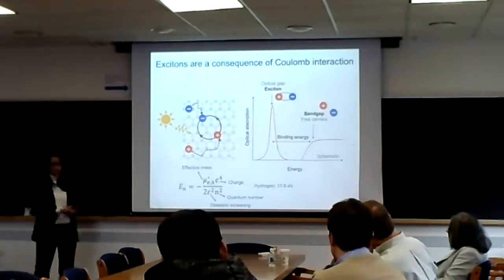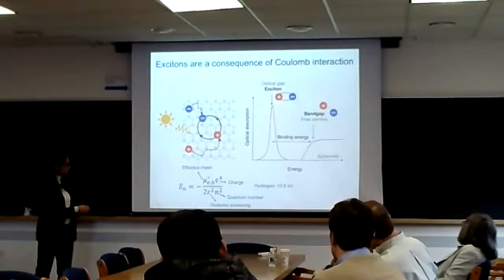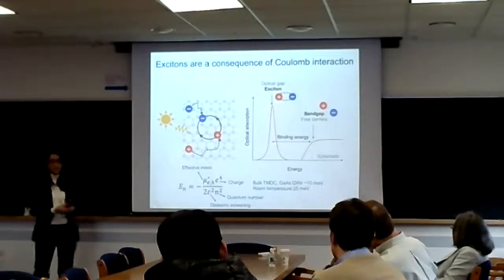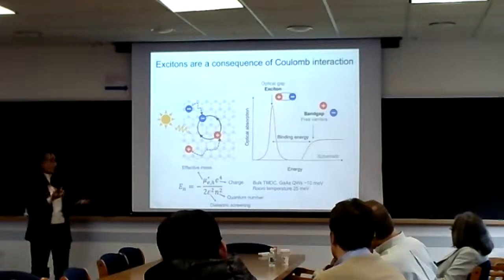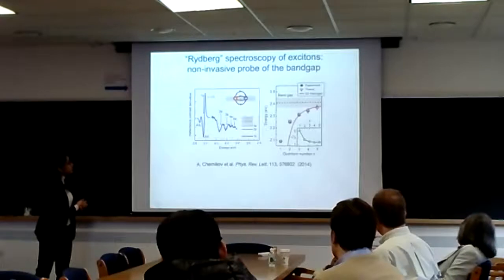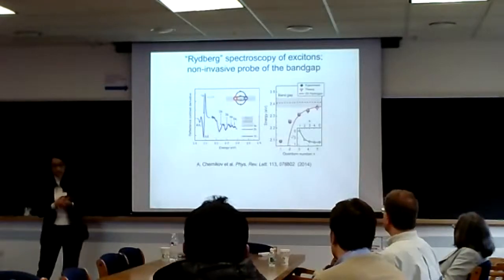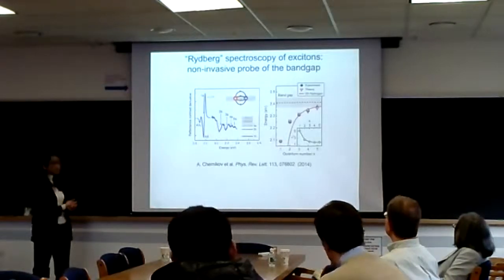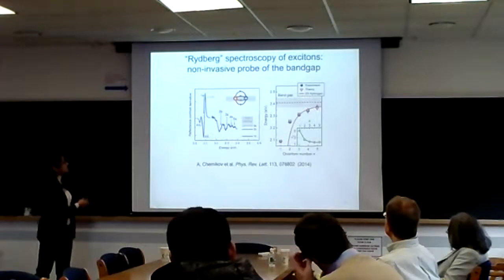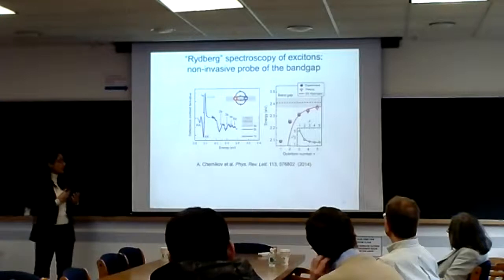Now let's work our way down to real systems of semiconductors. The effective mass goes down by an order of magnitude, and your screening goes up by an order of magnitude, and so you end up with excitons that have binding energy on the order of 10 meV. Now, in the case of 2D systems, it was shown here and in many other places that this binding energy is actually on the order of half an eV.